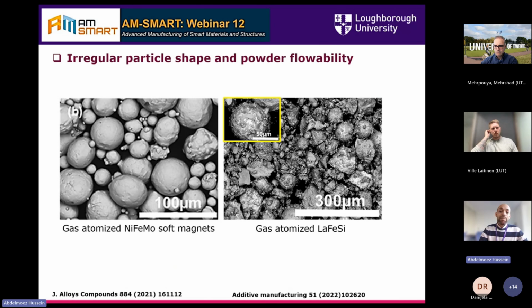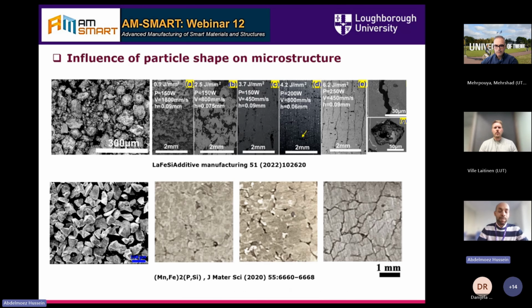How this powder shape can affect the material processing itself. Here are two examples of two magnetic materials, both pre-alloyed. You can see how ugly they are, and after processing, the first one can show a lot of defects related to the porosity, or even the cracking.